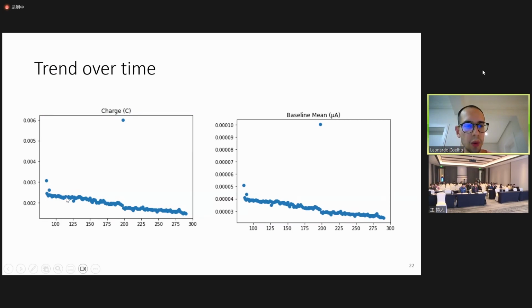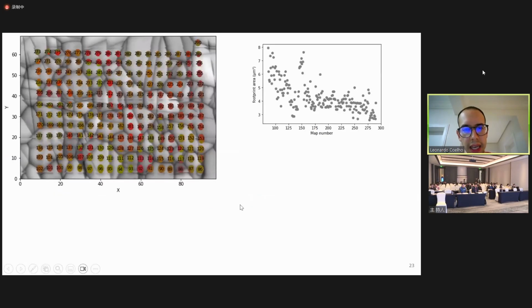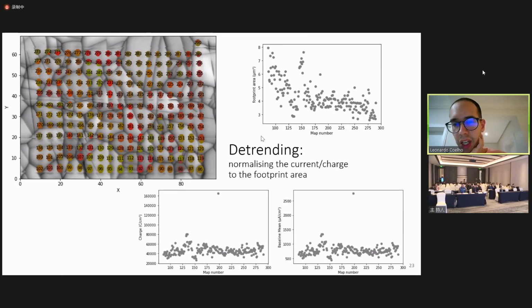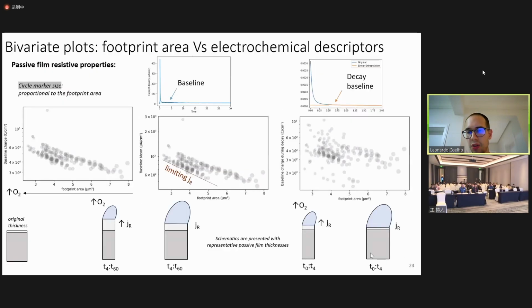There was a clear trend in the data, regardless of the descriptors we were looking at. There was a drift over time, and we realized that that was the case because the area of analysis, or the testing area, was shrinking over time. Here I plot as a function of test number the area of analysis, and we could clearly depict this trend. So although in the community, people using this technique express the measurement as currents, we decided to express it here for corrosion as current density. So domain knowledge helps us to, in fact, normalize all the current or charge data with respect to the area. And then we completely detrend, and we get the expected detrended data because of that.